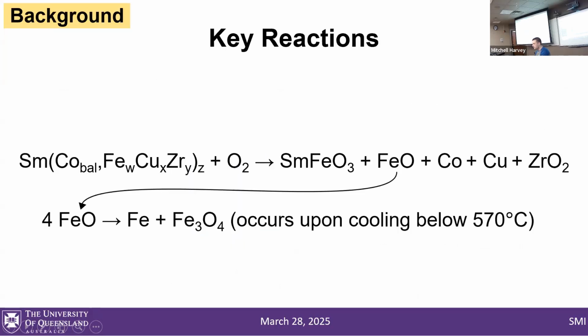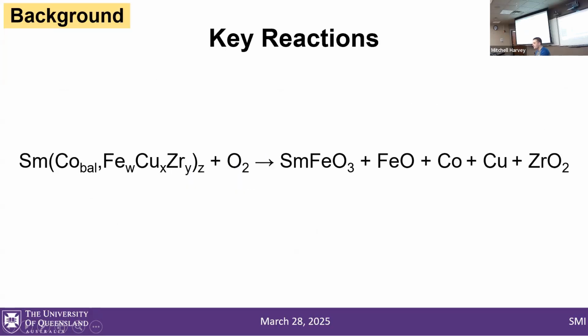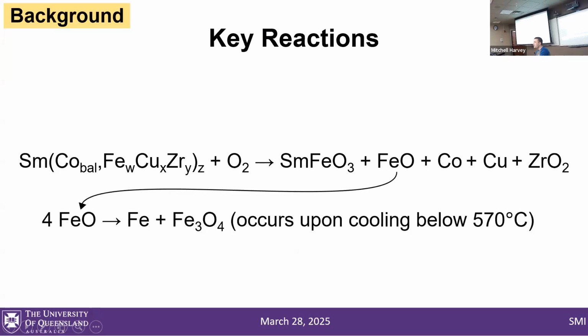So this is the overall reaction we're building to. We've got samarium, cobalt, iron, copper, and zirconium plus oxygen going to samarium ferrite, iron monoxide, cobalt, copper, and zirconia. Then the iron monoxide decomposes to iron metal and magnetite.